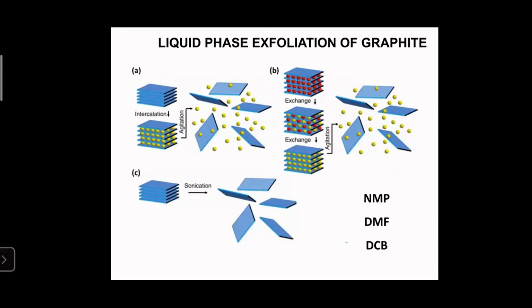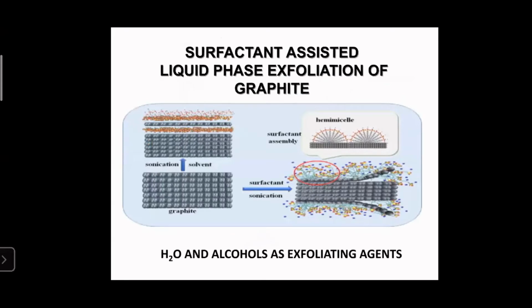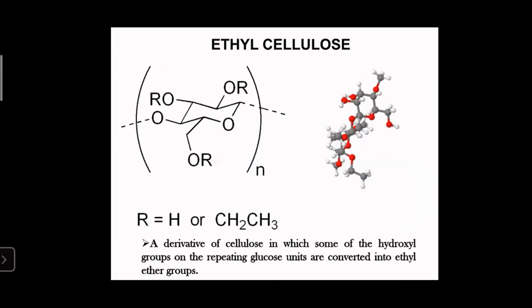Another way is to incorporate different species between the graphitic layers and then exfoliate further. Surfactants can be incorporated between the graphitic layers because surfactants possess both hydrophobic and hydrophilic ends. Graphitic layers can then be exfoliated using green solvents such as water and alcohols. This is the advantage, but the disadvantage is that surfactant removal is not easy and it can cause contamination. But here we use a perfectly green material, ethyl cellulose, for the exfoliation of graphitic layers to graphene.